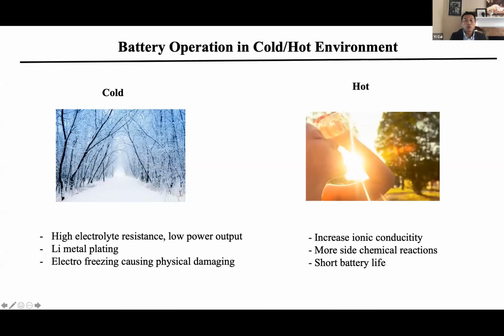And high temperature has a different effect. Of course, you have high ionic conductivity, but something you have to worry about is that the side chemical reactions increase. On the anode side, SEI, and on the cathode side, more oxidation. So you need to really pay attention to that. That can potentially shorten the battery life.